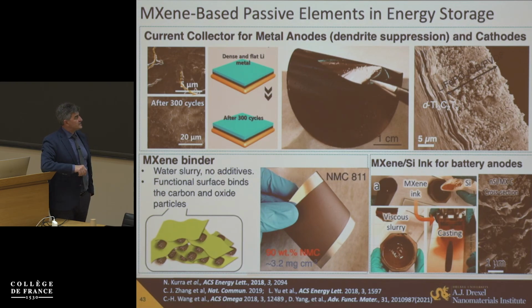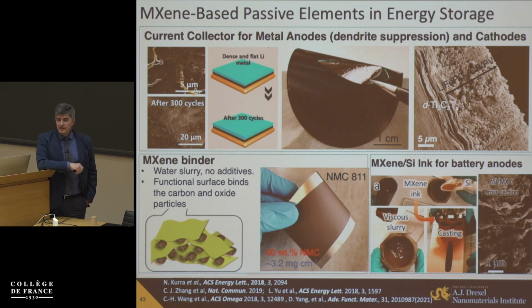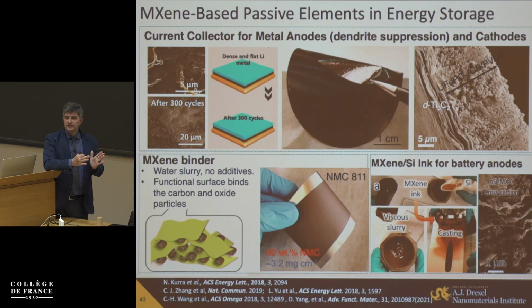Struggling a little bit to go over 60 microns of separation from metal here. But again, we can make these 3-5 micron current collectors and build on those, for example, LFP, LTO electrodes, simply making much thinner current collectors, especially for micro batteries, for batteries where you can actually make a thinner electrode. Just because now your current collector is thinner, you can pack a larger stack and get faster properties here. So binders, current collectors here.